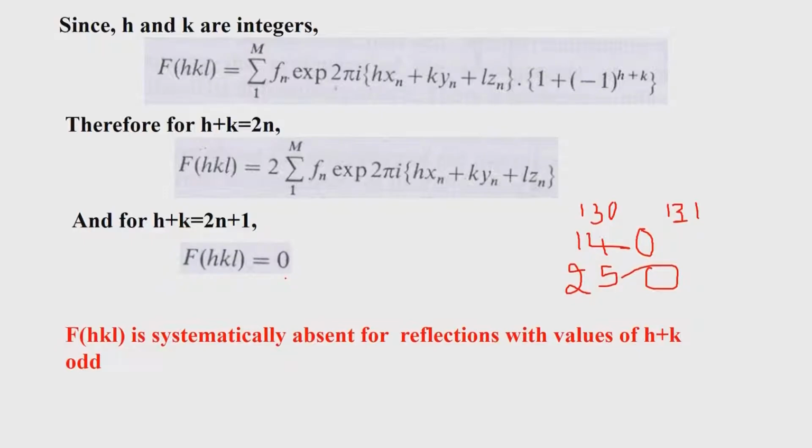So, now you see the importance of how diffraction can be used to identify the symmetry that is associated with the diffracting crystal. The system into which the diffracting material goes now clearly says that this has to belong to a C centered lattice, and depending upon the distances and angles, it could be either monoclinic or orthorhombic. Of course, the other symmetry elements which come are not associated with the centering, they are associated with the a, b and c directions depending upon the nomenclature we have for different crystal systems. So, that part we will discuss later.